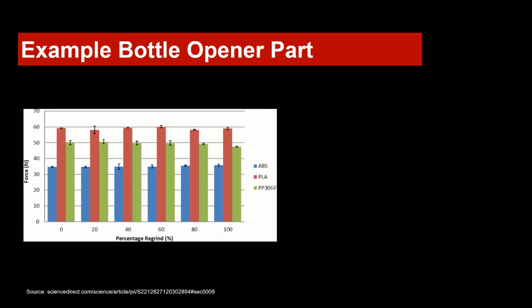And as you can see, we are staying within this 10% of loss of mechanical properties, which is really good. So in this case, this part can be really used with even 100% regrind. And so overall the polypropylene with the 30% glass fiber with 100% regrind is the option to go forward, evaluating all the results they found.